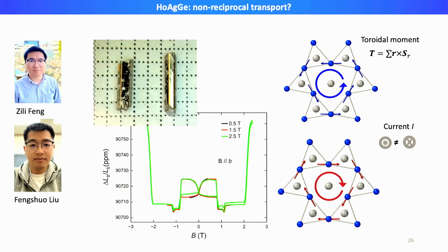Okay, so in this particular system, we are able to grow single crystals, which look like these prisms, and the cross section of these crystals actually corresponds to these distorted kagome lattices. Right, so here, thanks to magnetic frustration, a very exotic magnetic order is realized, where you can see that if